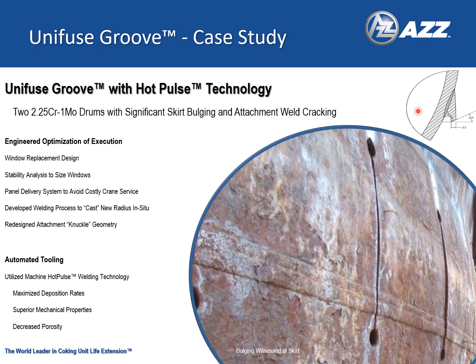AZZ developed a process to cast this radius in place utilizing a proprietary mold that was covered with weld metal and later removed. All of the welding in the repair area was performed using the Unifuse Groove™ process, and the weld deposit was volumetrically examined using linear phased array process. Once the knuckle was completed, the replacement windows were installed.